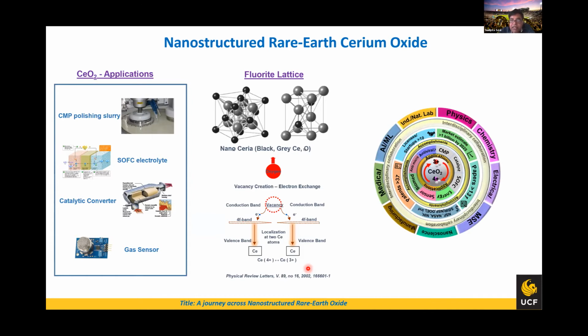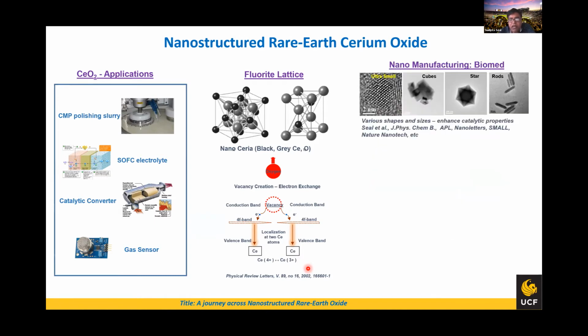And of course, this all happened due to interdisciplinary collaboration, and now we've really added artificial intelligence and machine learning with the Gary Best team to look into the materials design. So this is a structure of the material, the ultra small material that you can see almost got to 2 to 3 nanometers. You can see some kinks and edges around the surface, and this is where the vacancy is happening. And of course, the material becomes very active.